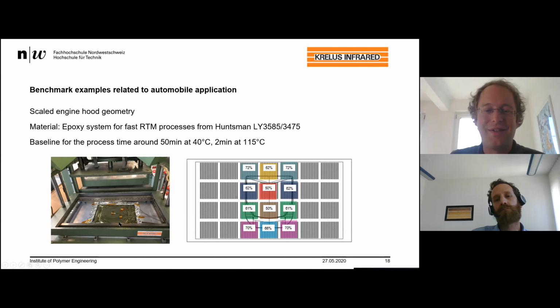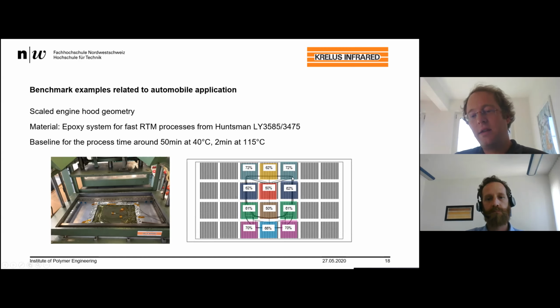And we applied it to a more complex, or not so complex structure, so we are a little bit limited in the size of the heating field. So therefore we scaled a kind of engine hood down to fit into our test case. And you can see again the distribution in the heat field, which was derived by the simulation.